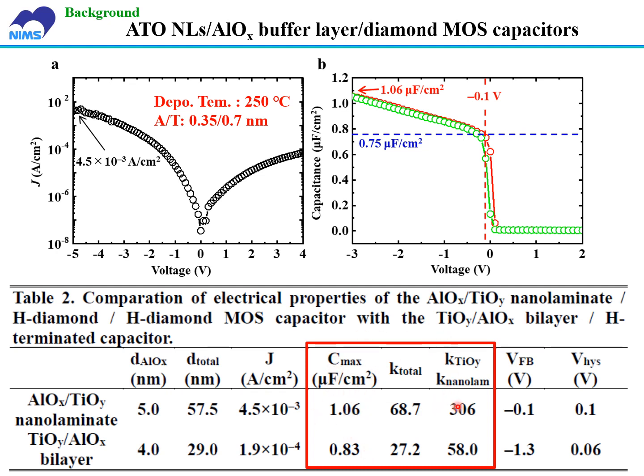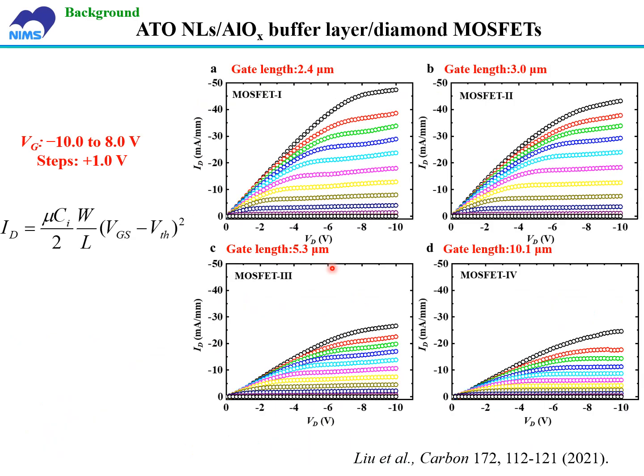The dielectric constants for the nanolaminate and the total insulator are also much larger than those of the bilayer oxide insulator or the single titanium oxide. We also succeeded in the fabrication of ATO nanolaminates, aluminum oxide buffer layer, diamond MOSFETs. With the increase of gate length for the MOSFETs, the maximum drain-source current decreased greatly. However, all of the MOSFETs show very good operations. Therefore, we have succeeded in the fabrication of ATO nanolaminate-based electronic devices.